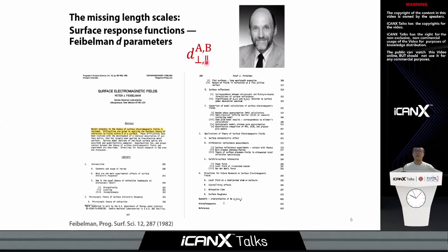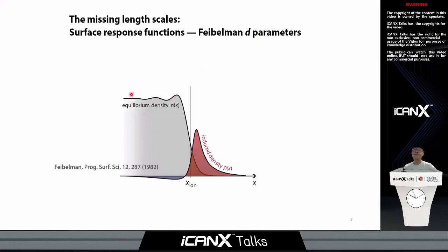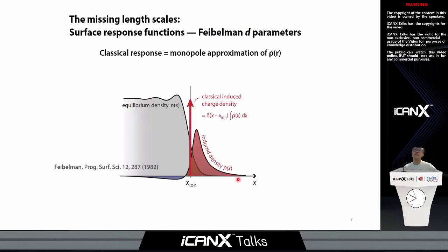So let me explain what this d parameter is. Let's think about this simple metal-vacuum interface, with metal on the left and vacuum on the right. You have this equilibrium charge density that gradually decays from the metal into the vacuum, as calculated from quantum mechanics. But in classical mechanics, this equilibrium charge density is assumed to be a step function rather than a smooth decaying function. As a result, under optical excitation, the induced charge density is given by a sharp delta function located exactly at the ionic interface. But quantum mechanically, the induced charge density does not do so. Instead, it has a non-zero spatial extent near the ionic interface, deviating from the exact interface.